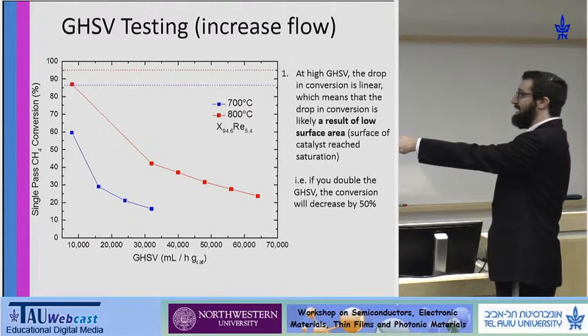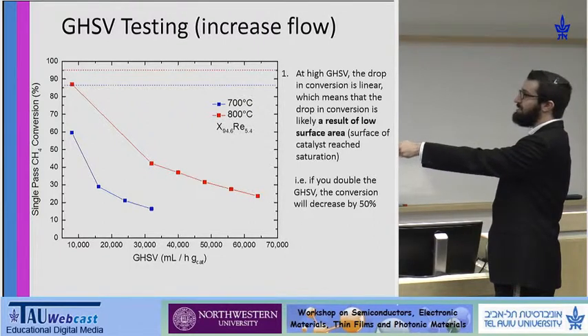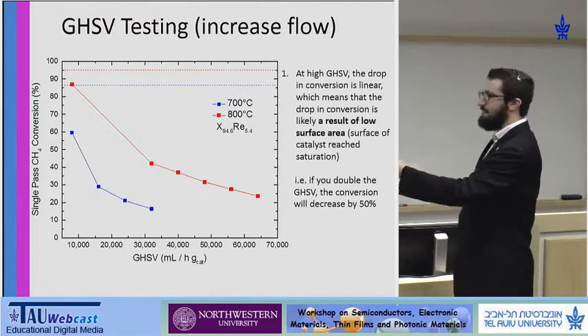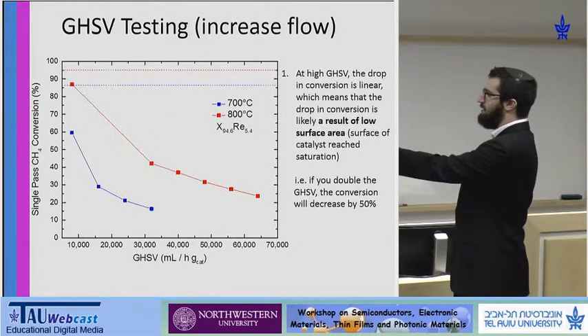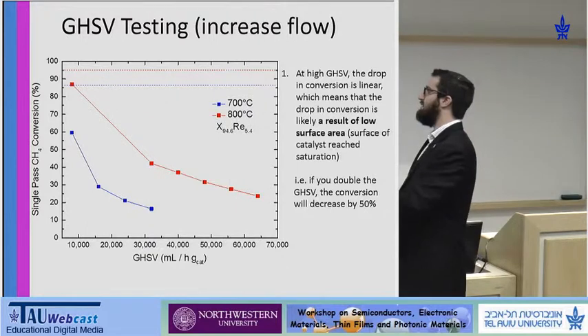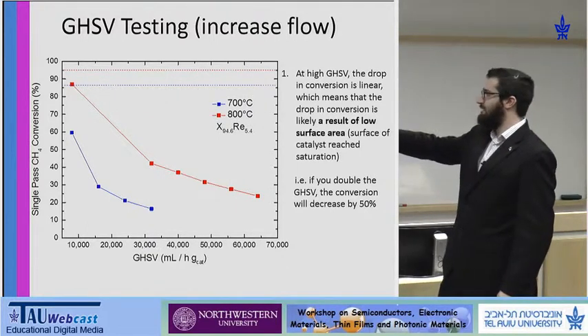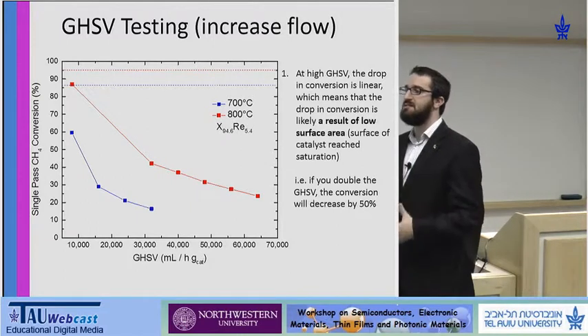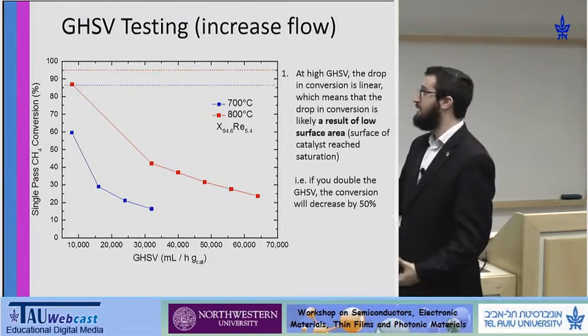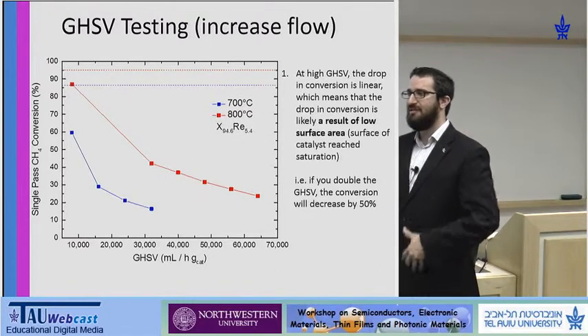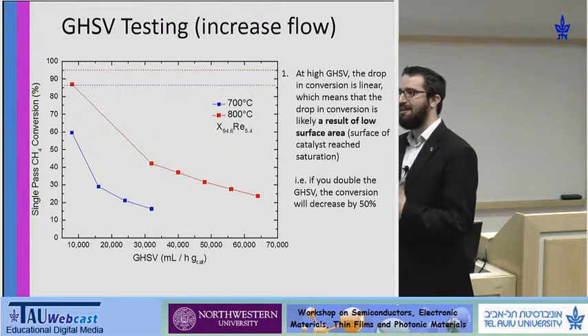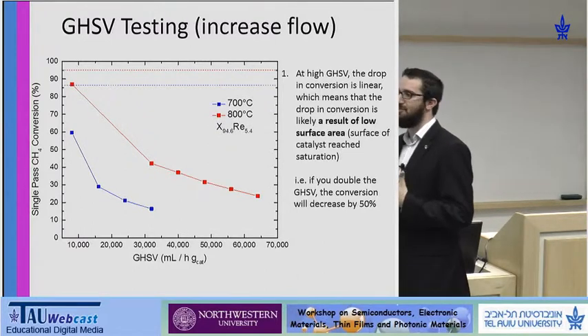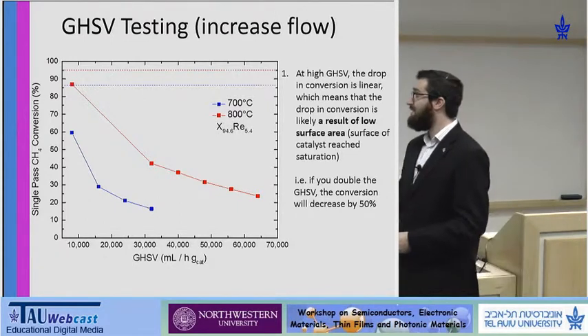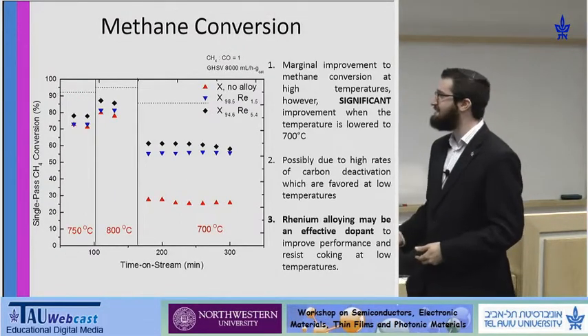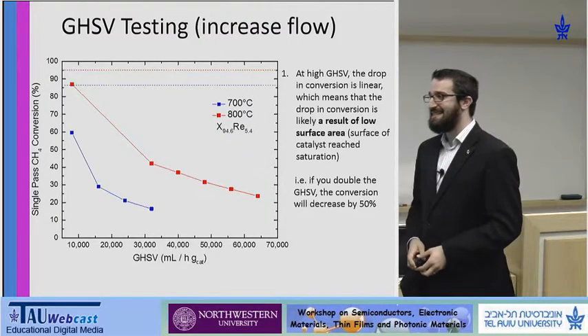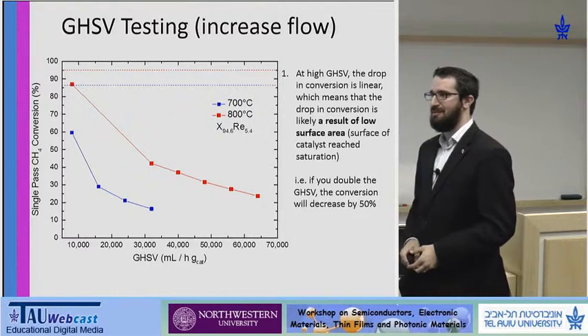What we see here is that as the gas hourly space velocity is increased to values that are typically used for powders, as opposed to metal meshes, the single pass conversion of methane drops significantly. But in the higher regime, it drops in a linear fashion, which means our surface is extremely active, but also saturated. It doesn't matter how much more methane you pass over the surface, all the active sites are taken up. You can't further increase the activity of these catalysts unless you change the geometry or the surface area. Nevertheless, we see that we have an extremely resistant catalyst that can perform at the same level as a powder if only its geometry can be changed.